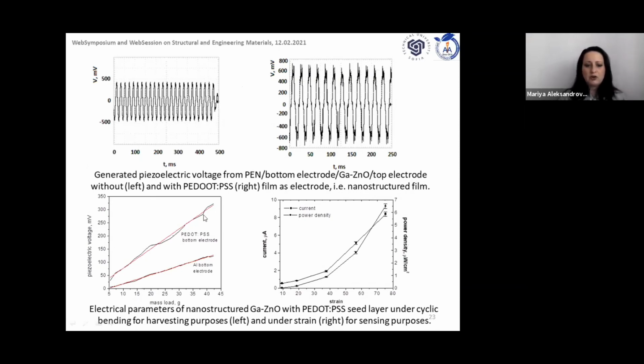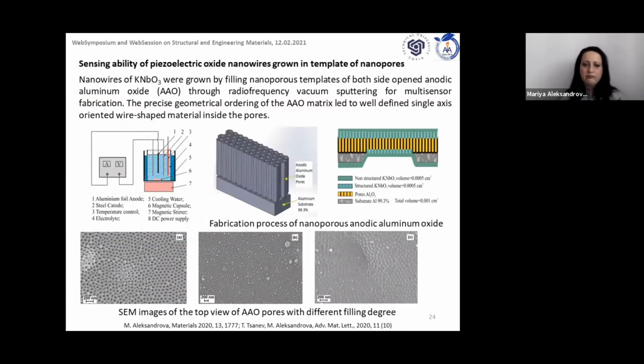Polymeric bottom electrodes still keep the linear dependence between the voltage and the mass loading, although they are less conductive. So it is suitable to work as a sensor, not only for dynamically changing mass loading, but also for static strain loading, although there is a little bit nonlinear characteristic here. And we believe that we can further improve the picture by orienting all nanostructures in a single axis.